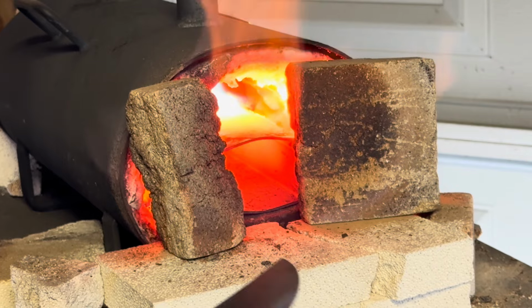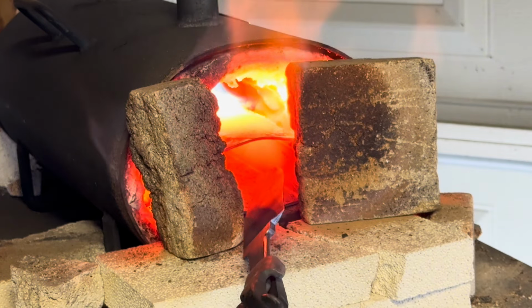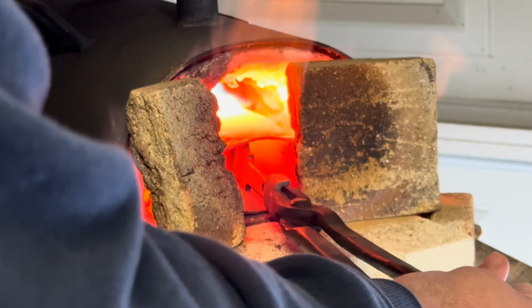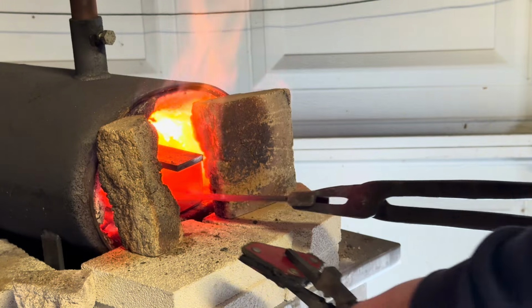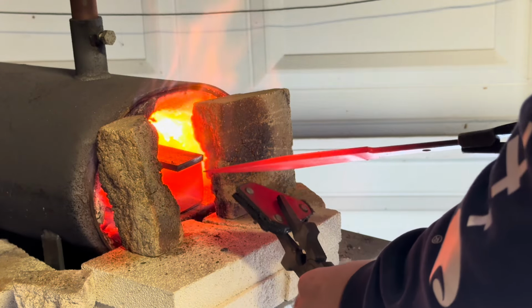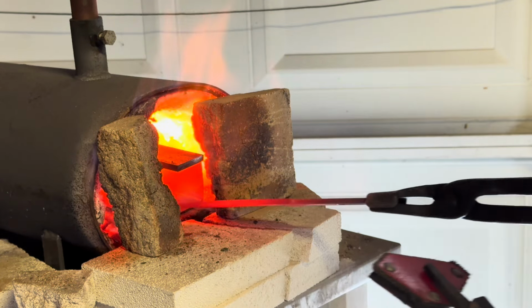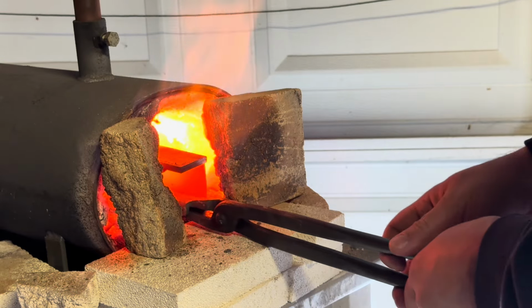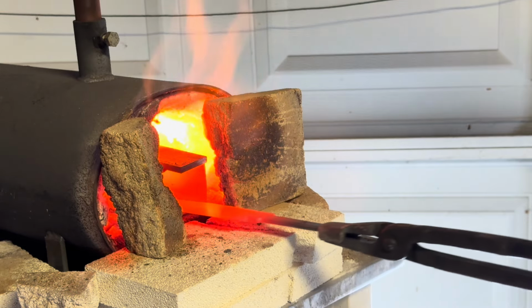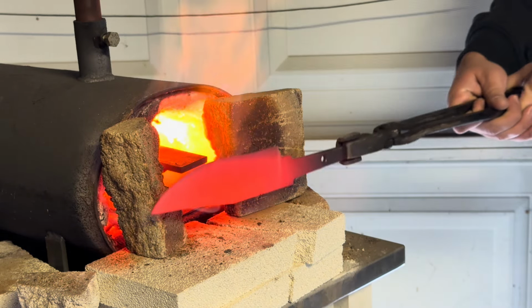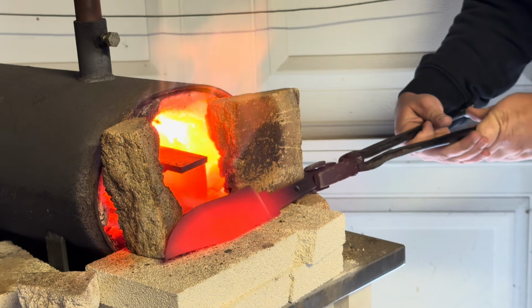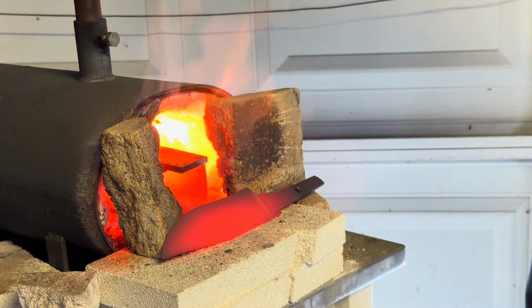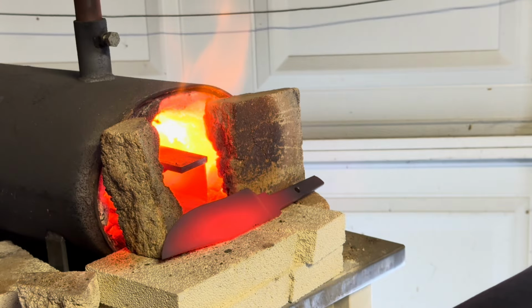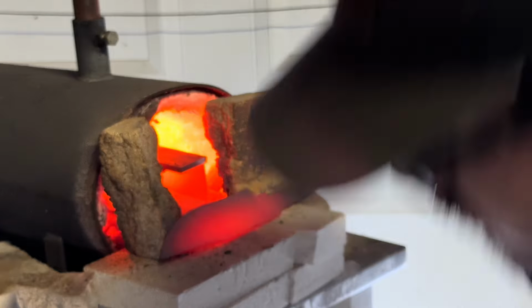With all the holes drilled and the rough grinding done, it's finally time to heat treat. Once the blade becomes fully non-magnetic, I take it out of the forge and let it air cool. This is called normalizing, and essentially it just resets the grain structure inside of the steel. It removes any sort of stress that might be in the steel, as well as evens out the crystal structure within. Once the blade has cooled to room temperature, I heat the blade back up and quench it in oil to harden.